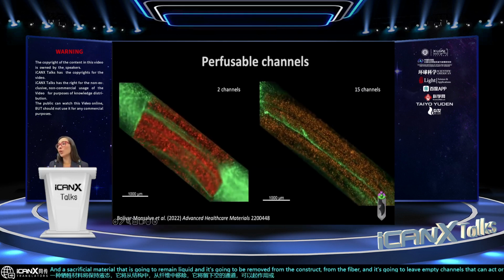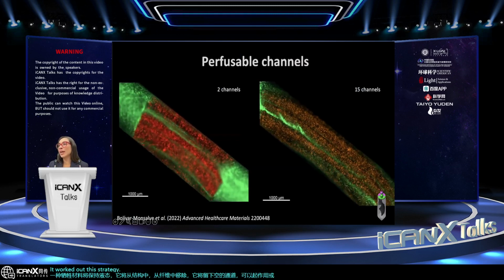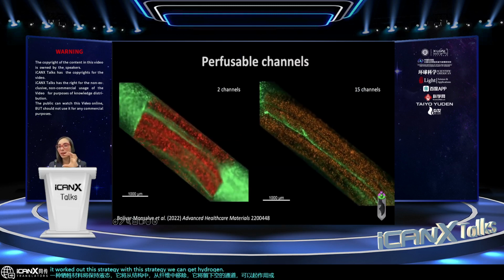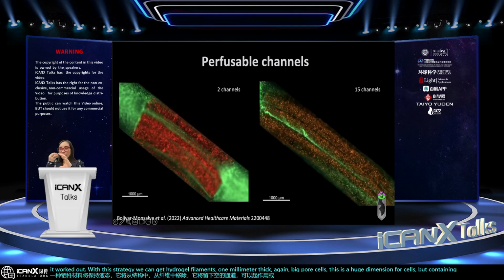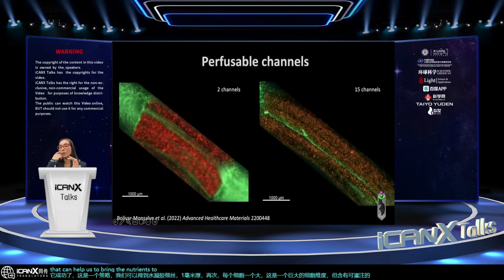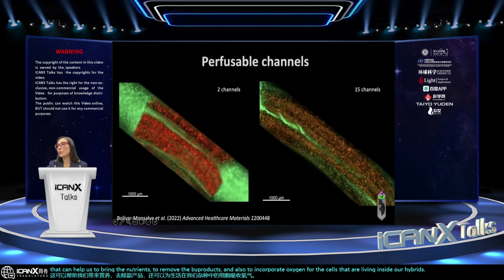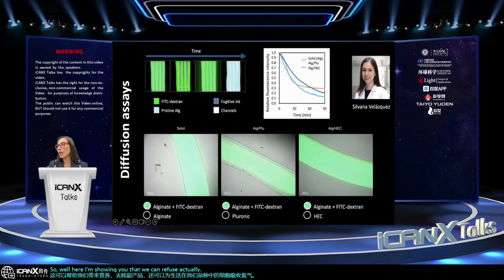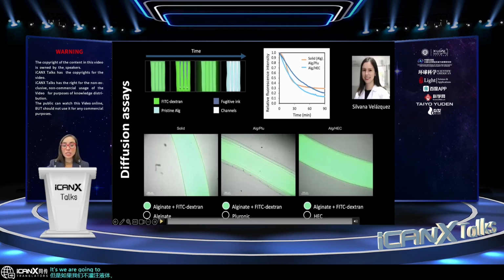So it worked out. With this strategy, we can get hydrogel filaments 1 millimeter thick. Again, big for cells. This is a huge dimension for cells, but containing perfusable hollow channels inside that can help us to bring the nutrients, to remove the byproducts, and also to incorporate oxygen for the cells that are living inside our hydrogels. So, well, here I'm showing you that we can actually perfuse the liquid through the hydrogels, but if we don't perfuse the liquid anyway, we are going to increase the mass transfer just by diffusion.